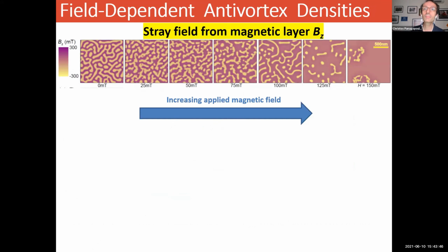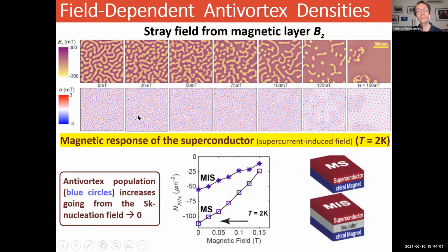Now you can look at the field-dependent anti-vortex density. What I show you here in the top row is the stray field coming out from the magnetic layer, and I go from left to right with increasing magnetic field. And in the bottom, I show you the magnetic response of the superconductor, again going with increasing magnetic field from left to right. And what you find is that the anti-vortex population inside your superconductor, that is these blue circles, increases as you go from the skyrmion nucleation field towards zero field, shown here in this plot.